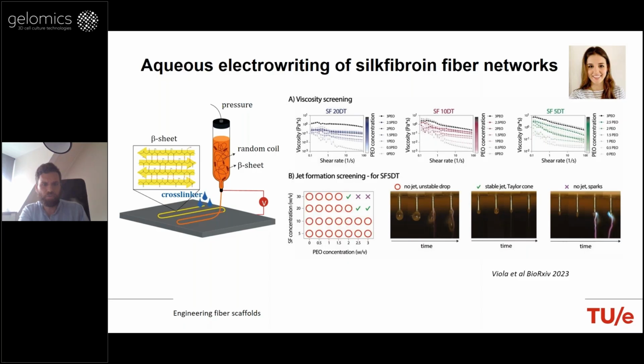So basically what we did was to explore the different boiling time of extraction. So we start from silk cocoons, and then we digest these cocoons in order to extract the silk fibroin, and control the molecular weight, and with the molecular weight control the viscosity, because viscosity is a crucial parameter for electrowriting. So there are basically three aspects that we should consider when developing materials for electrowriting. It's the rheological properties, mostly the viscosity, the electrical conductivity, because we are applying an electrical field, and the thermal stability of these materials. In order to control the viscosity, since we were looking at an aqueous-based material, we played with the boiling time, so the molecular weight and respective viscosity, and we also added viscosity enhancer, in this case PEO, that has a low electrical conductivity.